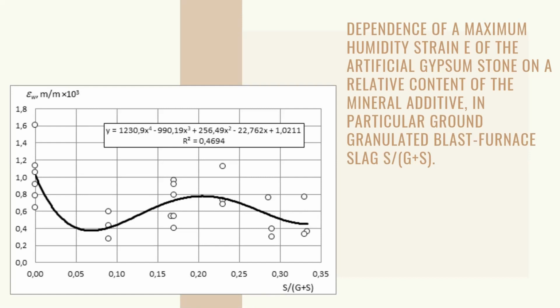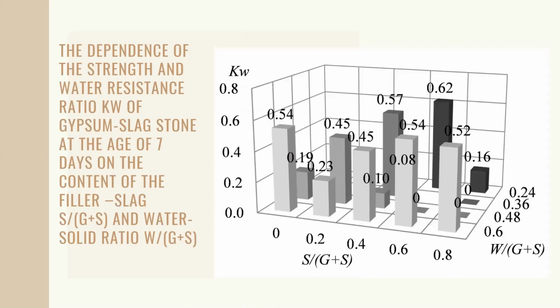Hence, it's reasonable to use the values of humidity strains of artificial gypsum stone as additional indicators of its water resistance. Therefore, the supplemental addition of granulated blast furnace slag to gypsum with the mineral additives results in no increase in the strength of artificial gypsum stone, and it can even condition a certain reduction of it. However, its strength is increased in the water-saturated state, and it results in an essential increase in the water resistance. The softening factor increased in the range of 0.6 to 0.8, and it can attain 1.